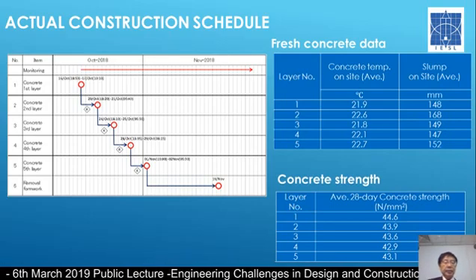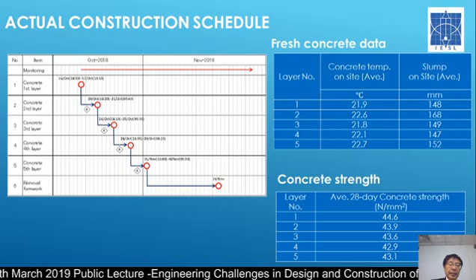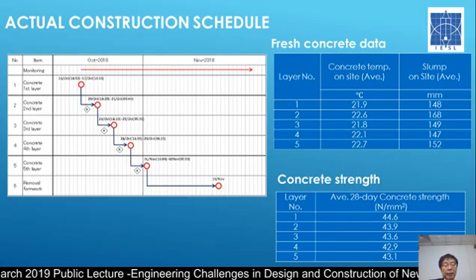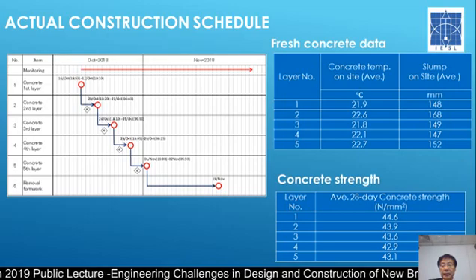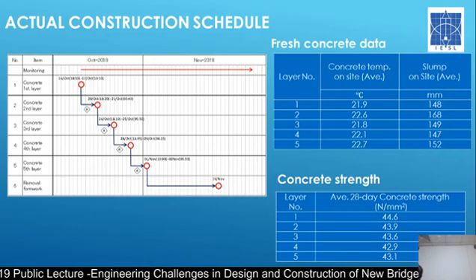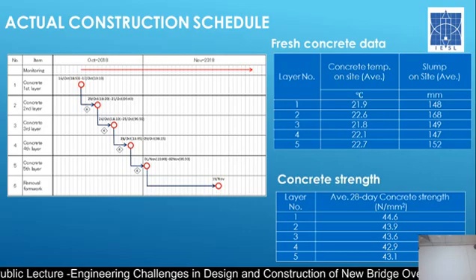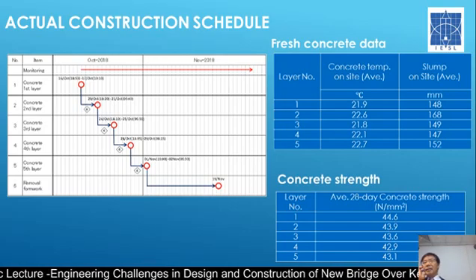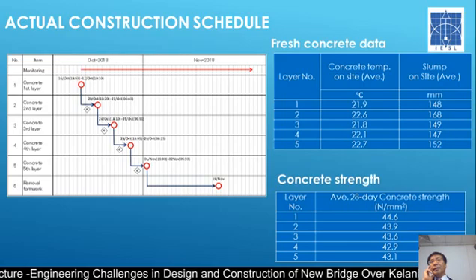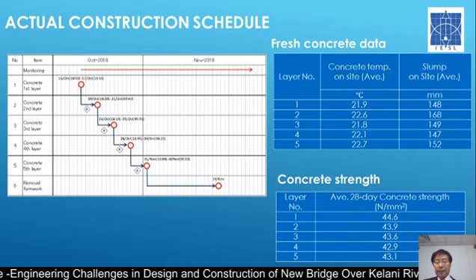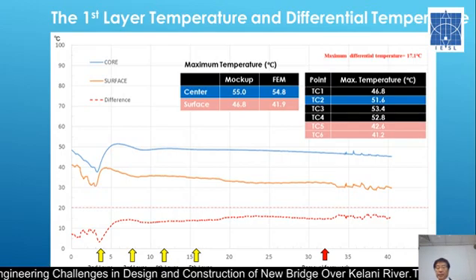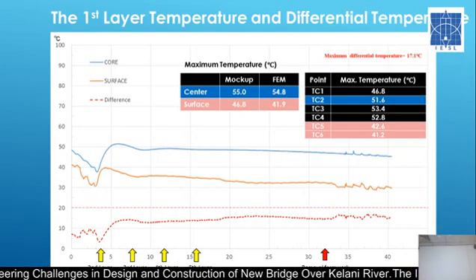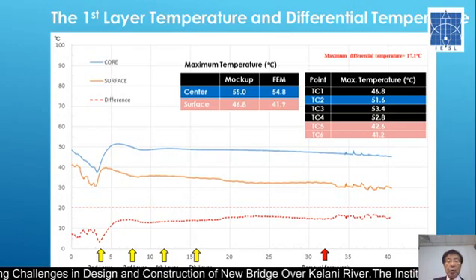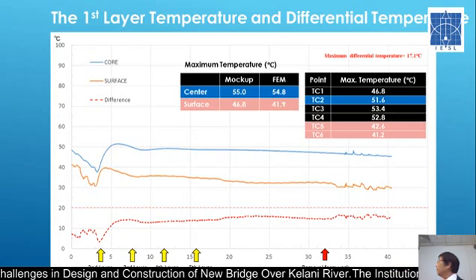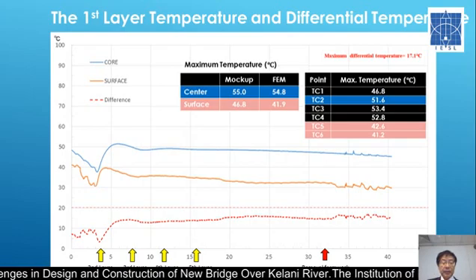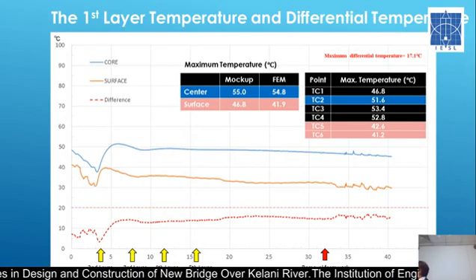And this is the actual construction schedule. As I said, the first layer casting and then basically a four-day interval between layers, to finish the concrete casting. The concrete temperature at casting was about 21, 22 degrees, less than the target temperature of 24.5 degrees. So this is a curve of how the temperature changes. The blue one is the core temperature, and the orange one is the temperature at the surface. And the dotted line shows the difference of the two.